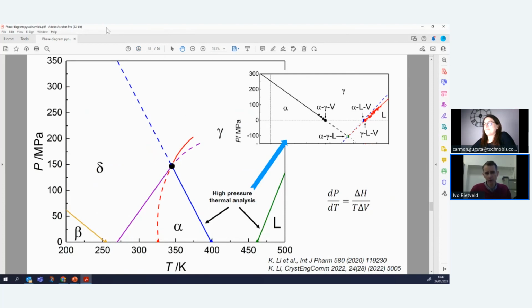So then you end up basically with a phase diagram that can look like this, where you extrapolate after that the slopes that you get out of the Clapeyron equation. Obviously, you will not find any new phases, because for that you really need to look at high pressure and see what the system does. But pyrazinamide doesn't move that much, so there is little to see in the sense of phase transitions.